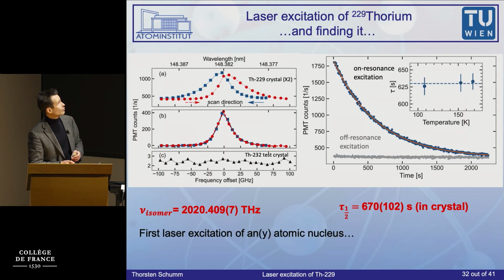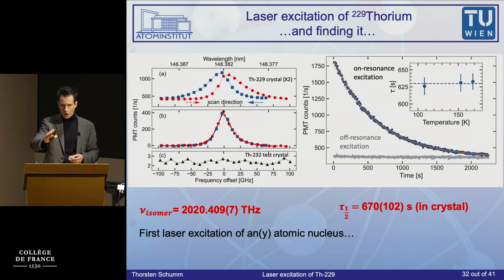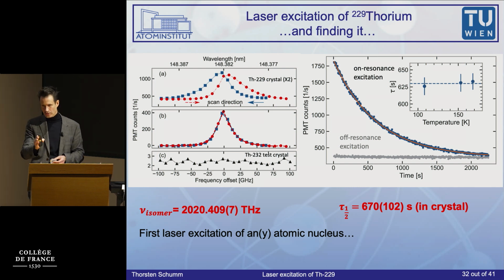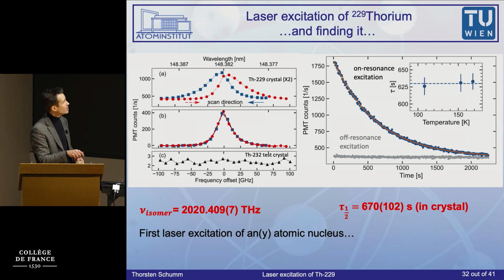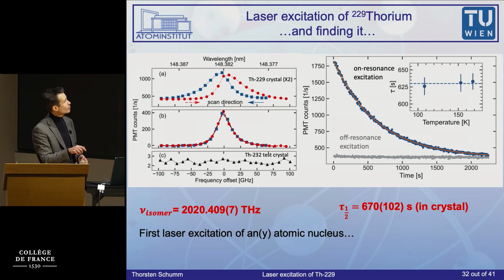So here it is. We scan the laser back and forth, and eventually at some point, we see a line. Actually, we were impatient, so we didn't wait long enough for all of the excited nuclei to decay before we detuned the laser. So that means there is a hysteresis, so that depending on which direction we scan, there is a memory effect, and the line is slightly shifted. But if we are patient enough, then that dependence goes away. So that means ultimately we know the transition wavelength or frequency to 2 gigahertz precision from that experiment.